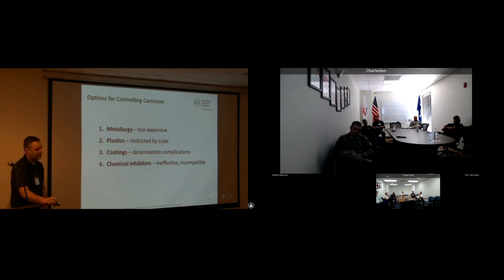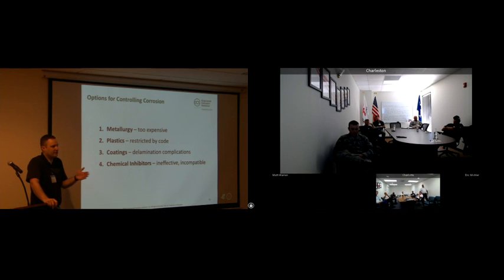Chemical inhibitors, we tried very early on. The problem with chemical corrosion inhibitors, they work really great in flowing regimes where we have a transmission pipeline, because they're designed to be carried by whatever you're transmitting, oil, water, whatever, through the pipeline. So there's always a dosage in whatever you're transmitting through the pipeline to reapply if we ever get a breach in that chemical corrosion inhibitor on the pipe wall.